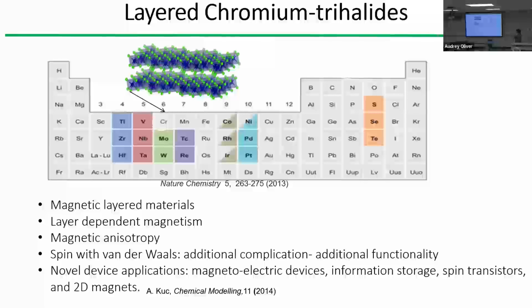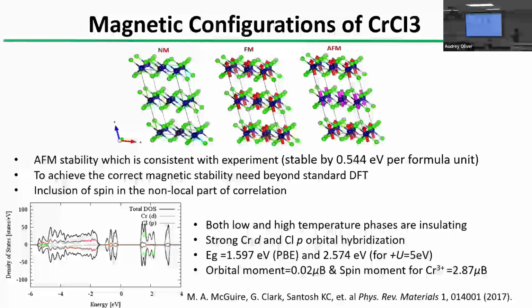as well. Okay, and then if we have iron or ferrous material, if we have magnetic materials, it's more complicated in terms of calculations because you need to take that magnetism into account as well. But there are more novel device applications as well. I'll give a simple example. This is the crystal structure of chromium trichloride, and you can calculate considering this non-magnetic, without including the spins, or you can make this ferromagnetic, or the spins align in one direction or opposite directions like this, and calculate